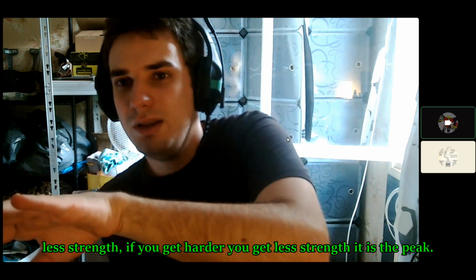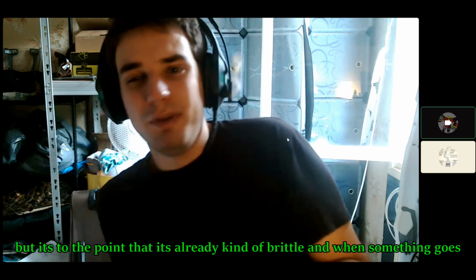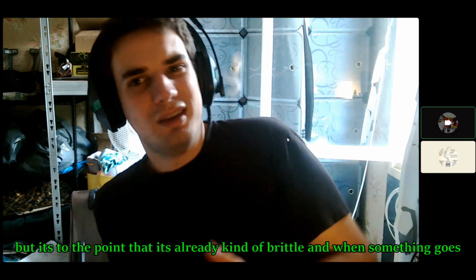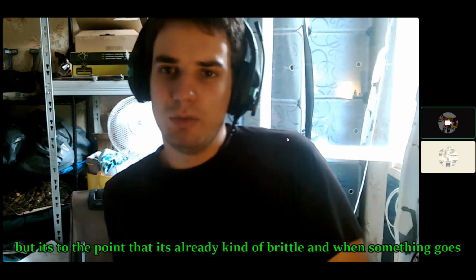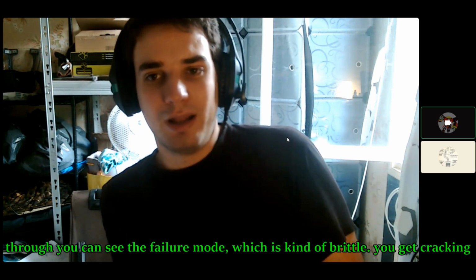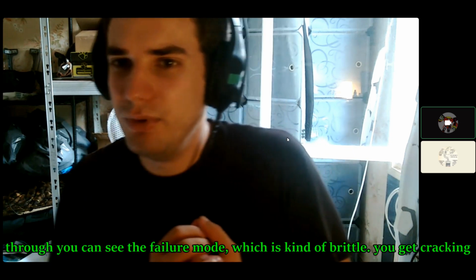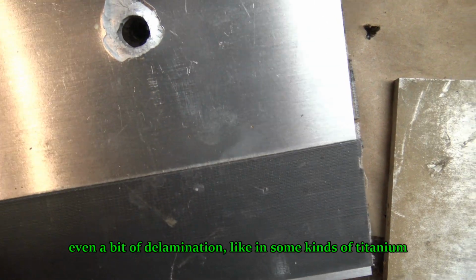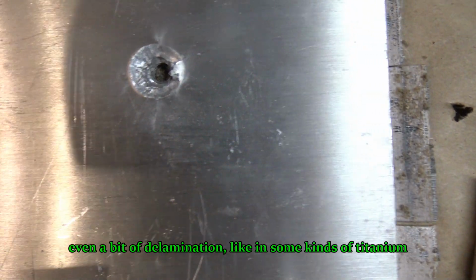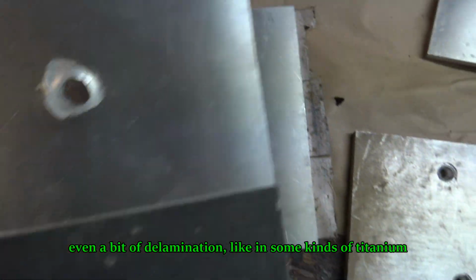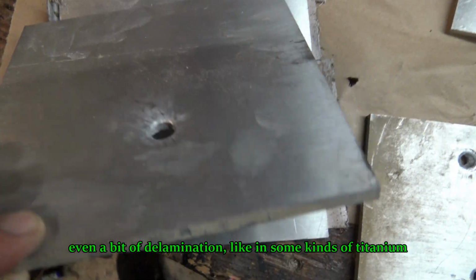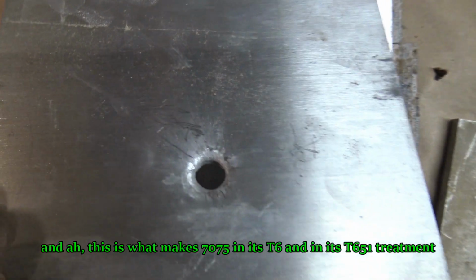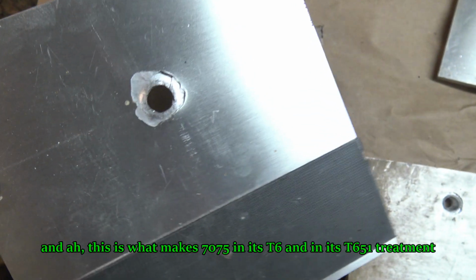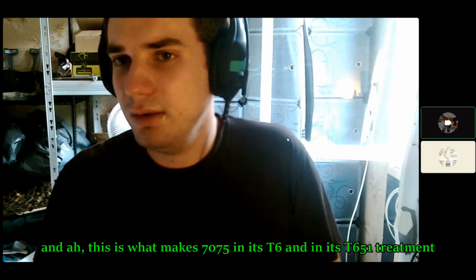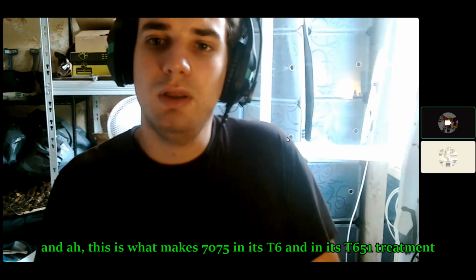If you get harder, you get less strength. It is the peak, but it is a point where it is already kind of brittle. And when something goes through, you can see the failure mode, which is kind of brittle. You get cracking. You get even a bit of delamination, like on some kind of titanium. So it is kind of a peak. And this is what makes the 7075 in its T6 and in its T651 treatment